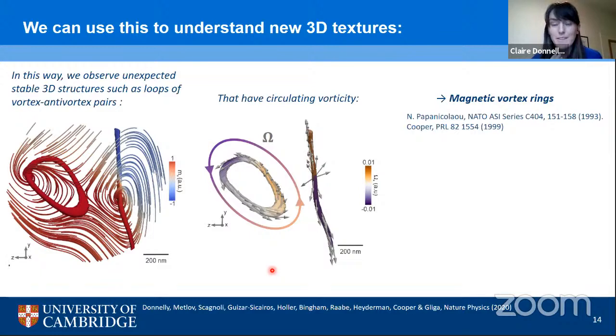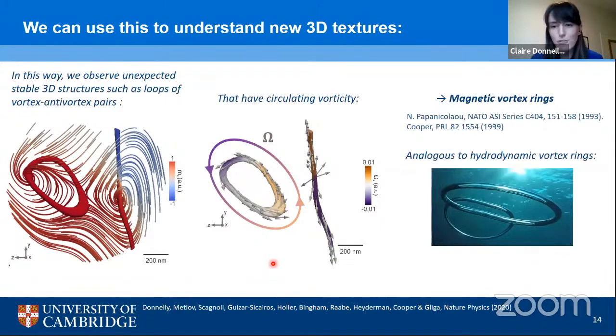Now, there's another particularly intriguing fact about these vortex rings: analogous to their hydrodynamic equivalent, they were predicted to be dynamical objects. So they were not predicted to be stable when they were static. And of course, in this sample, in our pillar, we have a measurement that takes at least 50 hours. So we definitely have these samples. So we have this intriguing stability, essentially, of these magnetic vortex rings.